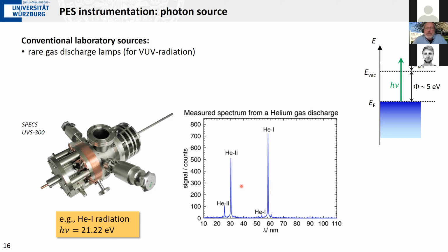You can either try to monochromatize your light by using a monochromator, which always costs you a little bit of intensity and also a lot of money to implement, or you just live with these satellite structures in your spectra. And sometimes you see this when you look at published photoemission spectra, that you have an echo or a second image of your spectrum shifted by a certain photon energy, and that comes from these satellites here. But once you are aware of their existence, it's easy to identify them.